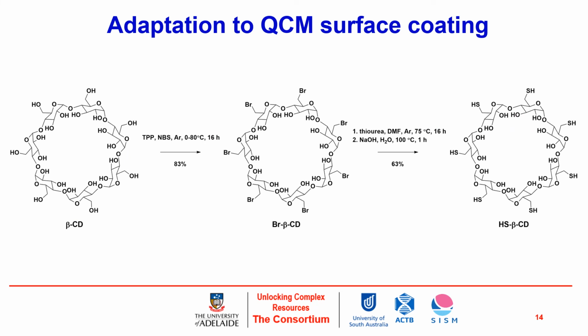So to overcome the issue of not being able to apply these particles directly to the quartz crystal microbalance due to their size, attempts were made to see if we could reduce that particle size. Sadly, we reached a bottom limit and it was still too high. So back to the synthetic drawing board, I took beta-cyclodextrin and modified it by replacing those hydrophilic rim hydroxyls with bromine substituents, and with those bromine handles in place, bromides can be exchanged quite readily. They're what we call in chemistry a good leaving group. So we're able to take these and synthetically exchange them for another group. This was done in a two-step reaction with thiourea, and then reduced to the sulfhydryl groups, or SH, shown on the right-hand side of the slide, to provide those thiols that we're looking for as handles for attachment to the gold surface.